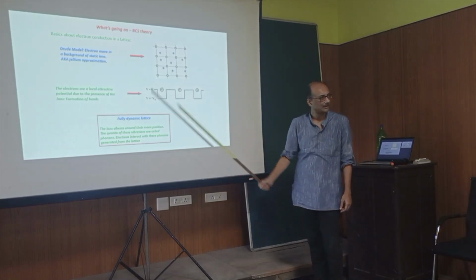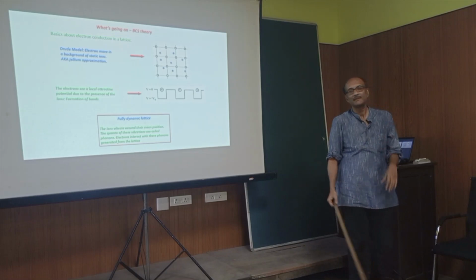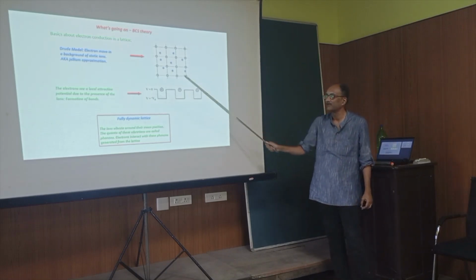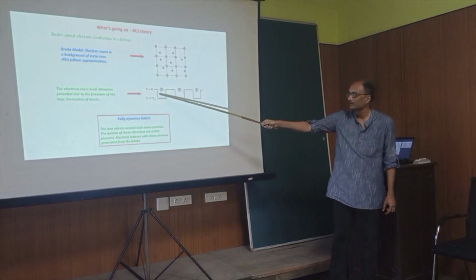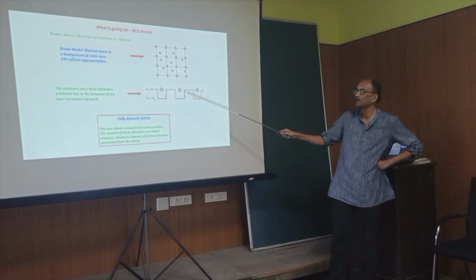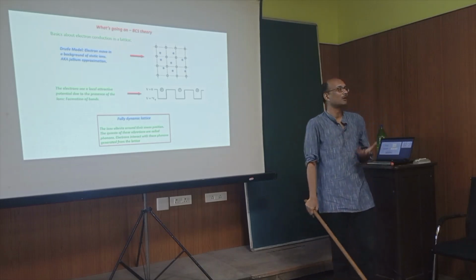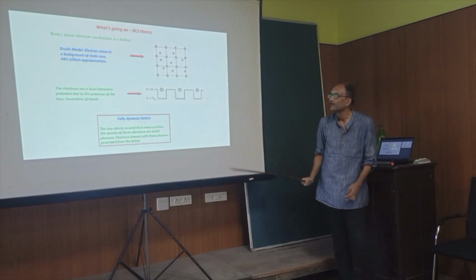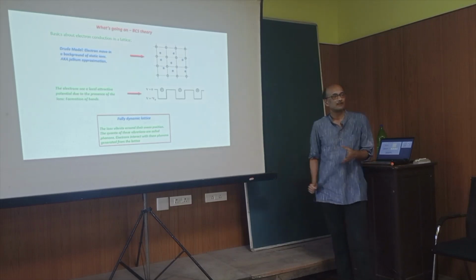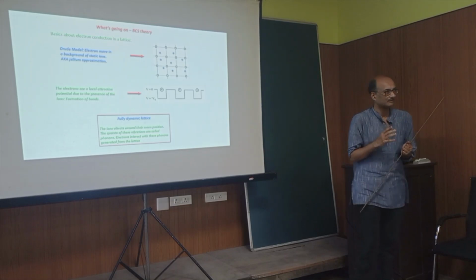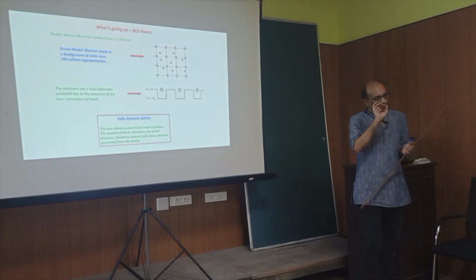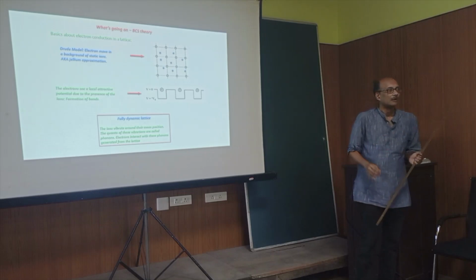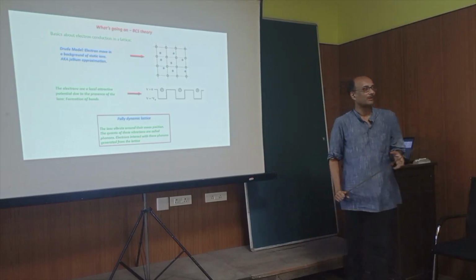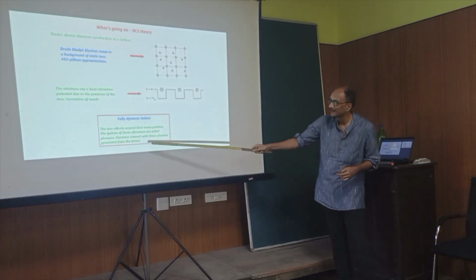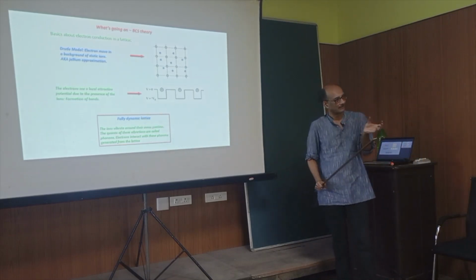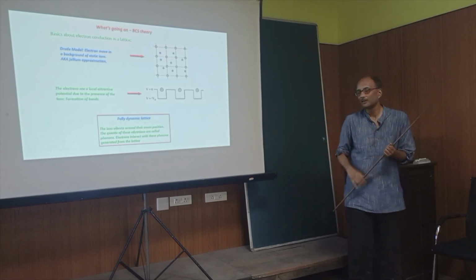However, of course, this is not entirely true because as we know in a metal there is this lattice and the ions are arranged in a specific pattern. So this, for example, is your typical potential well, but lots of them. That's one model which explains this lattice. The point is that the lattice, it turns out, is not static because these ions move around their mean positions. So it turns out that it is fundamentally important to explain superconductivity that these electrons see this moving lattice, that is, the vibrations of the lattice, which are typically called phonons.